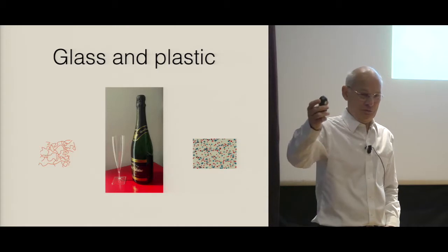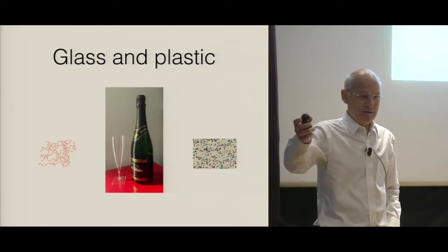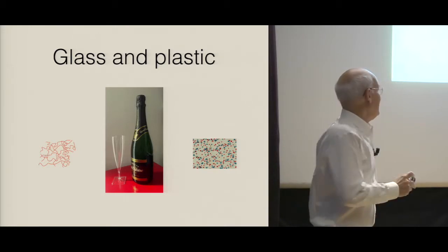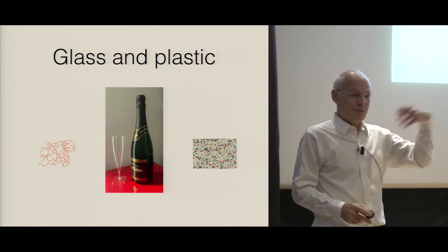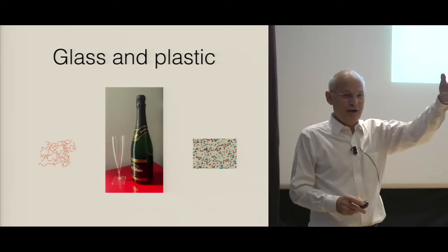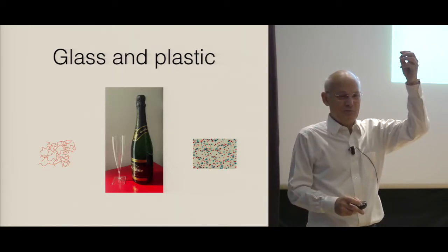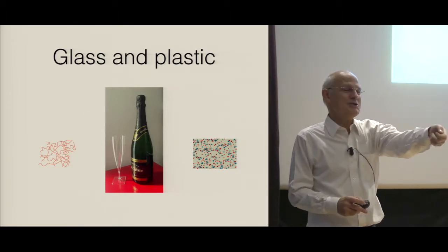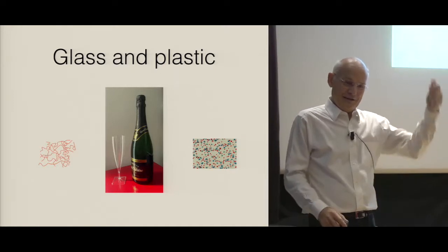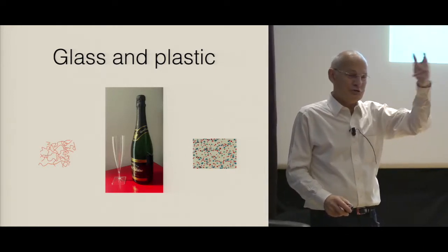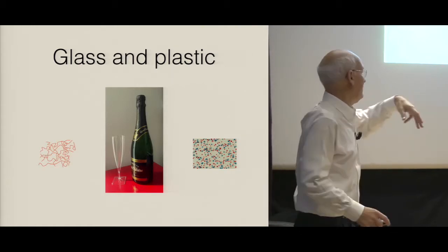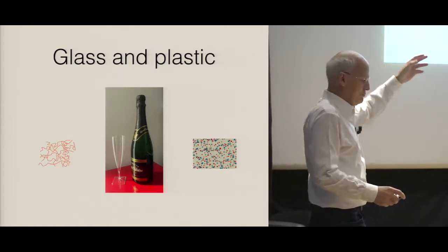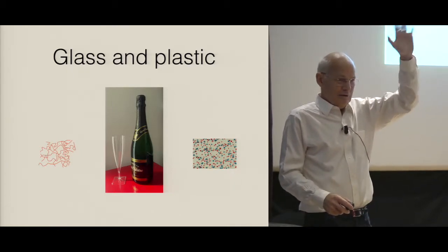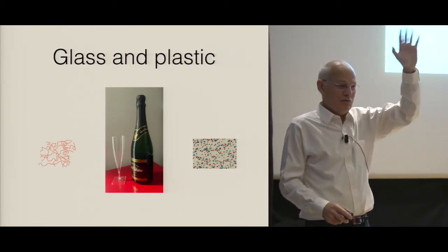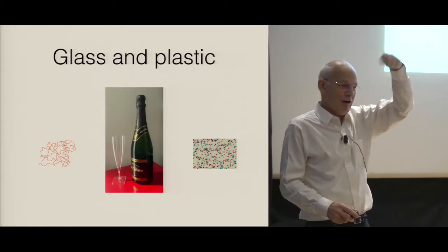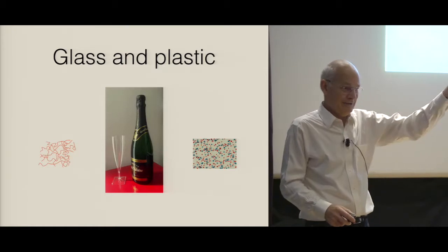People wanted to develop glassware from plastics, but the reason why it didn't develop is that you cannot wash it. You cannot put a polystyrene glass into the dishwasher because it will become white and break. And if you look at the plastic glassware in your kitchen, or at the mixers and things like that with plastic parts, they often become very beautiful and transparent at the beginning, but then they have plenty of small cracks and they become hazy and